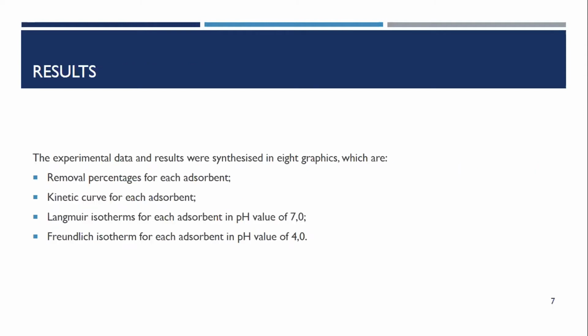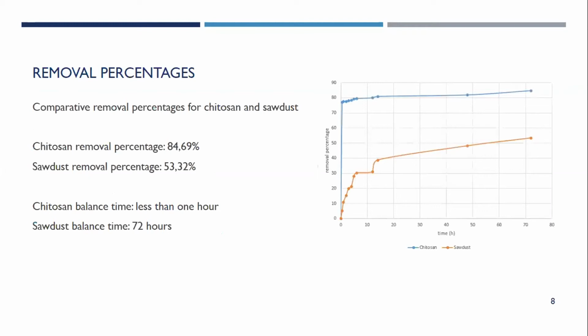The experimental data and the results were synthesized in 8 graphics, which are removal percentages for each adsorbent, the kinetic curve for each adsorbent, Langmuir isotherms for each adsorbent at pH value of 7, and Freundlich isotherm for each adsorbent at pH value of 4. Here we see 2 graphs, which are the comparative removal percentages for Chitosan and Sawdust, in which Chitosan is shown in blue. These results led to the conclusion that the removal percentage for Chitosan is 84.69%, while the Sawdust removal percentage reached 53.32%.